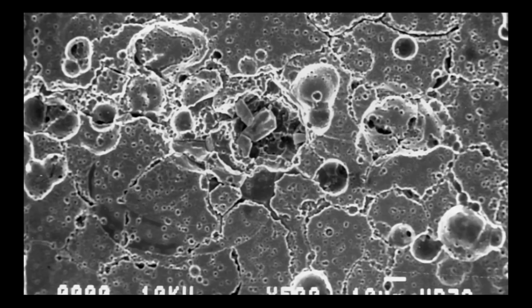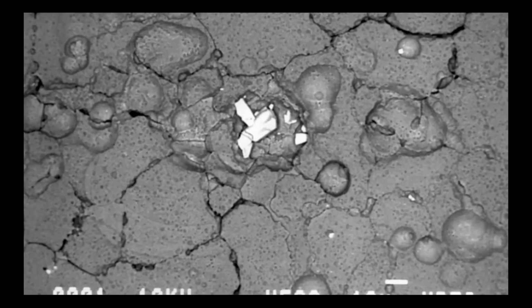Now, if we clean the sample with nitric acid, we can remove this white corrosion product, and there we see the pits beneath each of the chimneys. And inside the pits, we can actually see the second phase particles, which are lit up here in this image.